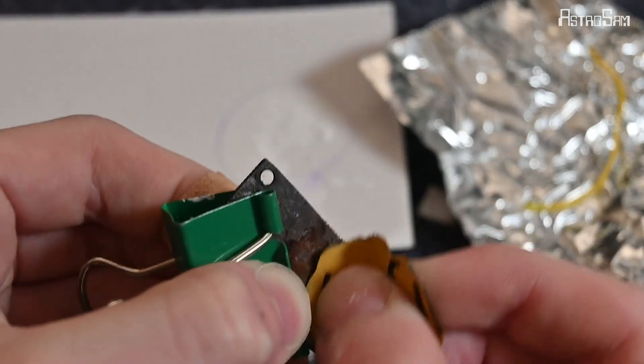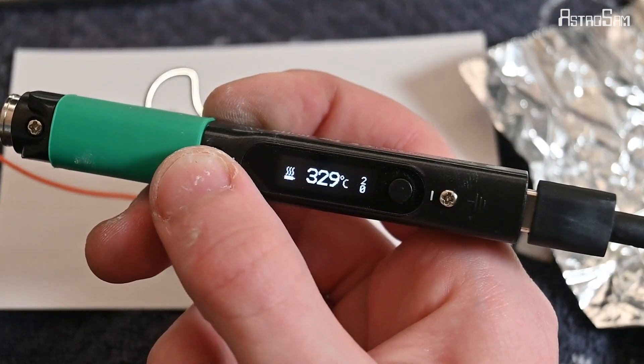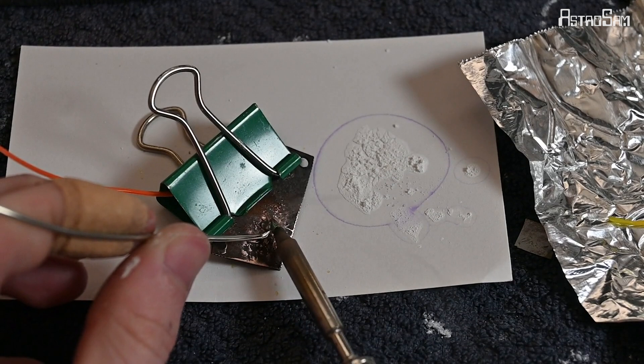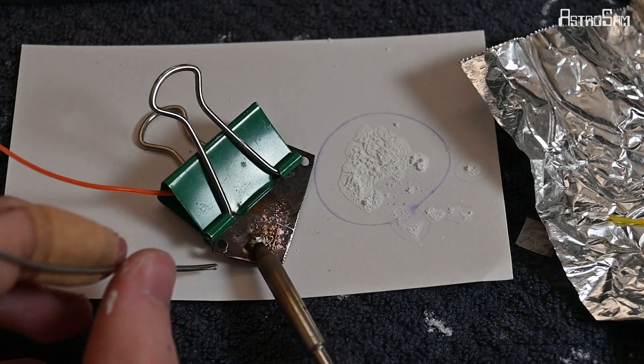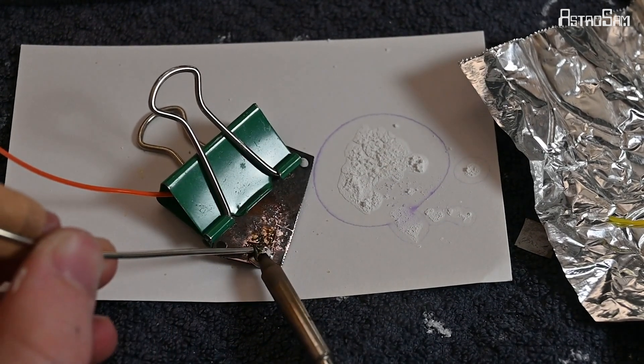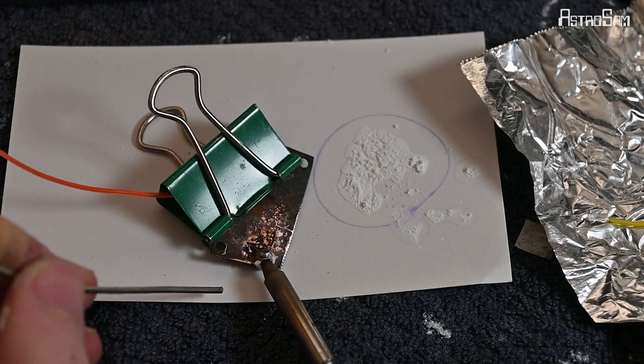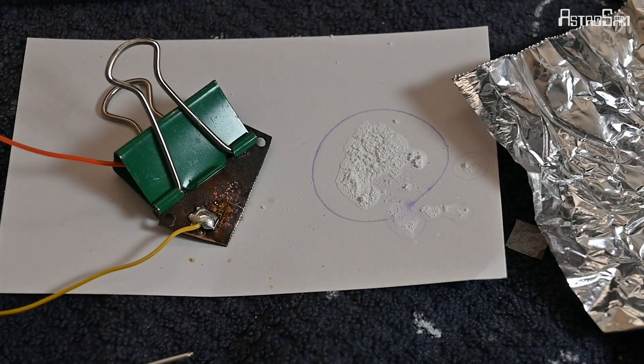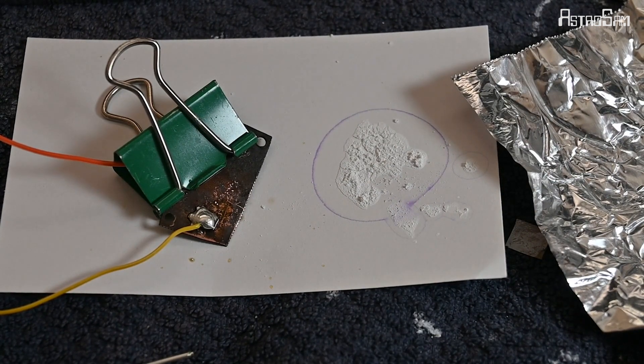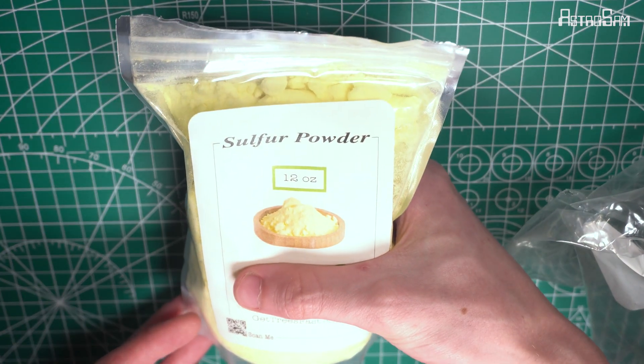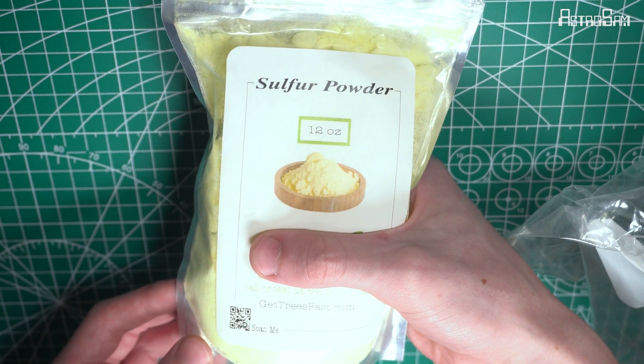Unfortunately, this did not really work out. I wouldn't use titanium dioxide in its raw form — I think you really have to sputter titanium directly onto a surface for it to work well. I believe this process to technically be possible, but it requires a better substrate, should be done in a vacuum chamber, and at very high temperatures. So instead, I tried the first method I actually researched, which is the copper sulfide method.